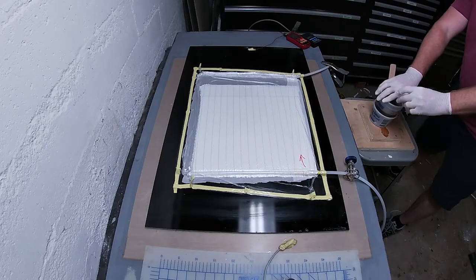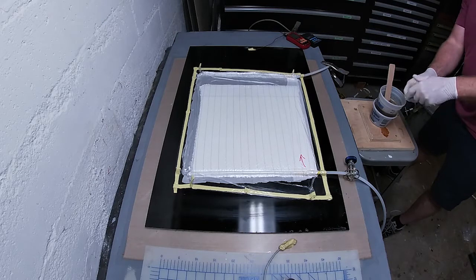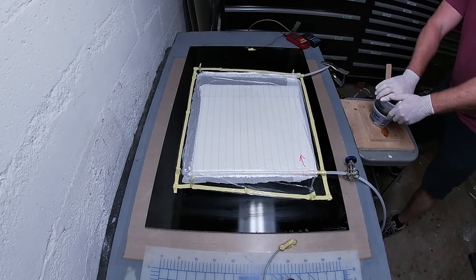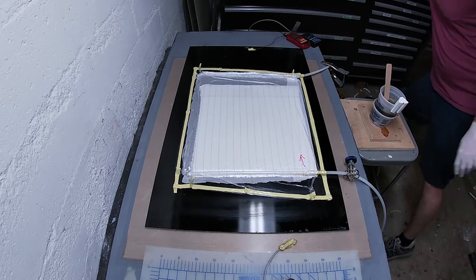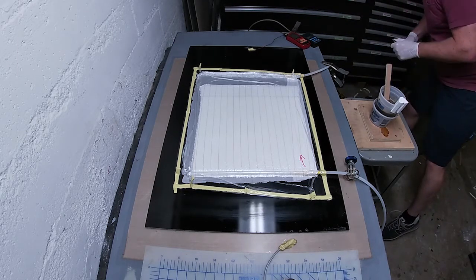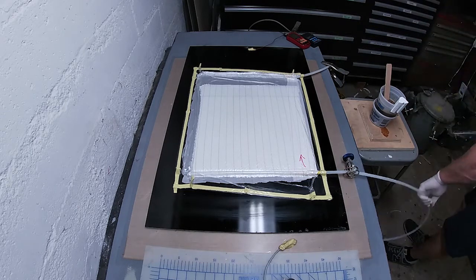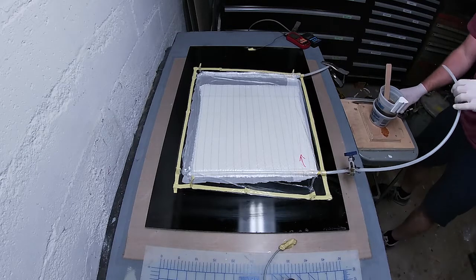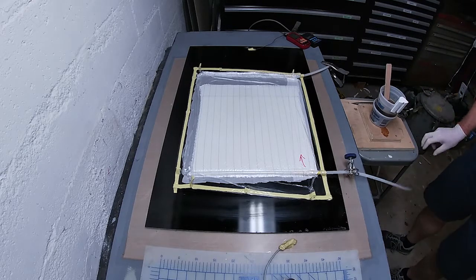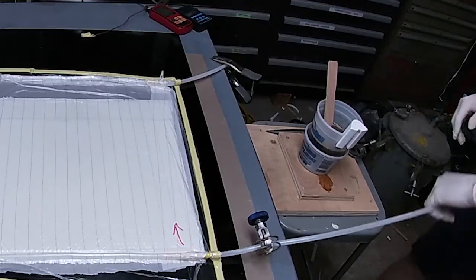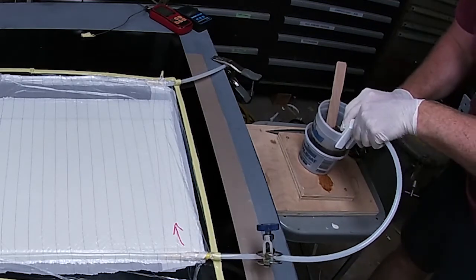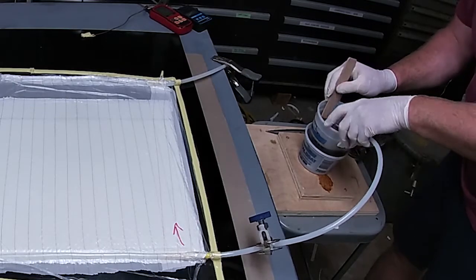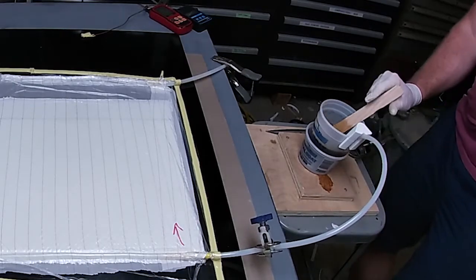But the resin itself is relatively cool in the pot. It's probably room temperature which in this was about 65 fahrenheit and I'm using this little infusion clamp and I'm going to cut a little bevel on the end of the hose at 45 degree which helps keep it from butting into the bottom of the cup. This little guy you can slide the hose through, it just holds it in there. This is one I made up, other people make them. I put the model on GrabCAD if anyone wants it.